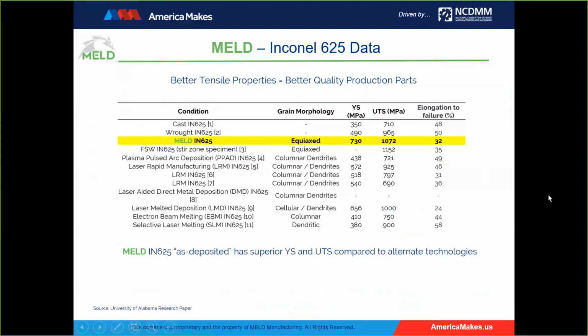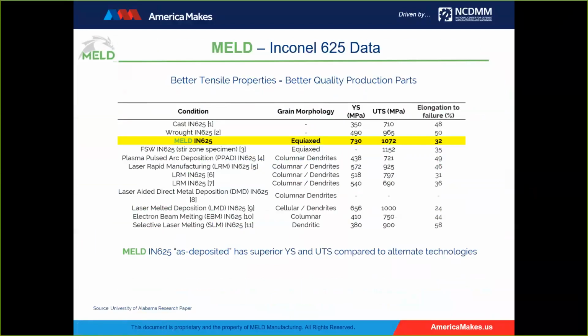Let's see if I have one more slide on that. Oh, sorry. So I want to kind of hit that. Any metal type. Well, Inconel 625 was chosen as a coating application, fully dense, no porosity, no voids, no HIP, no vacuum furnace. Fully dense means there, from a corrosion perspective, no pathway for corrosion to work back to the surface.